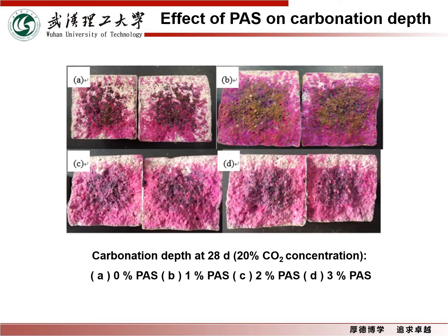Then we show the results on the effect of PAS on carbonation resistance of slag blended pastes. The carbonation experiment was performed according to Chinese standard. Blended pastes were cured for 28 days before carbonation. CO2 concentration was 20%.